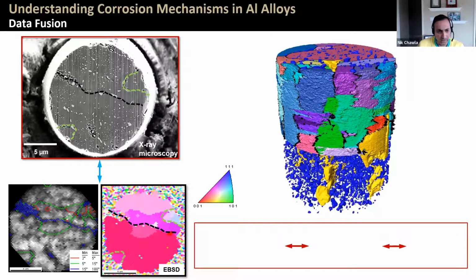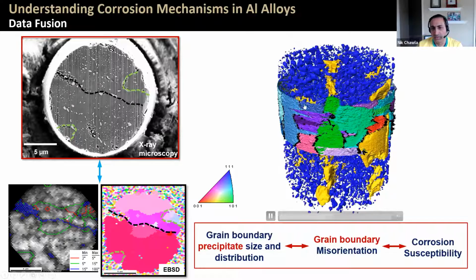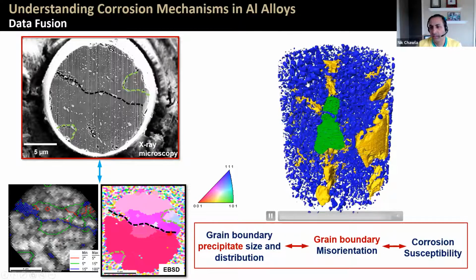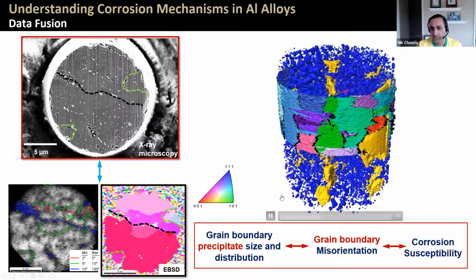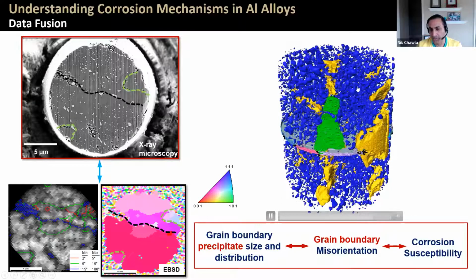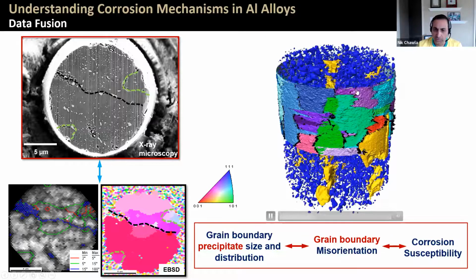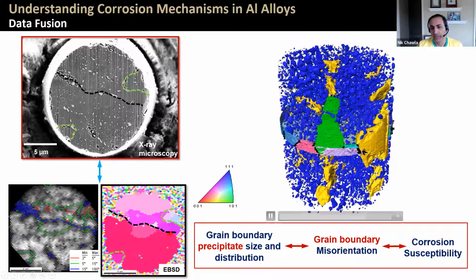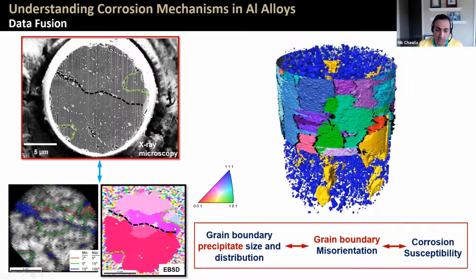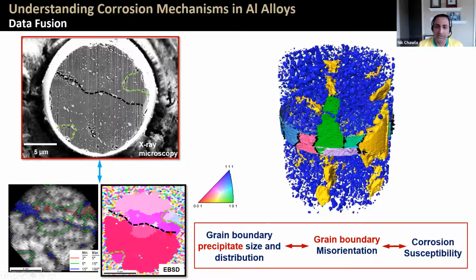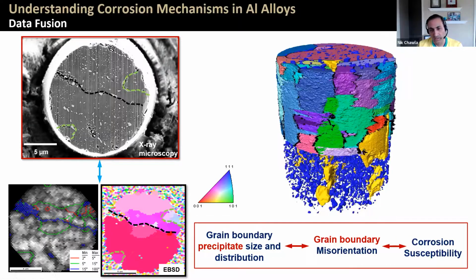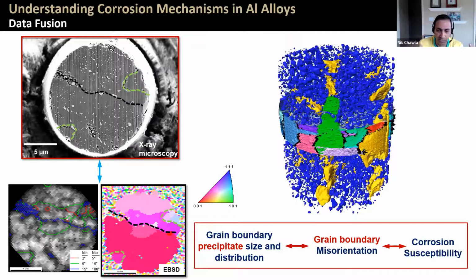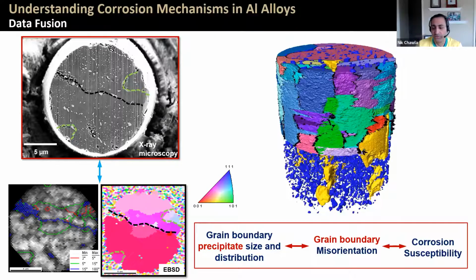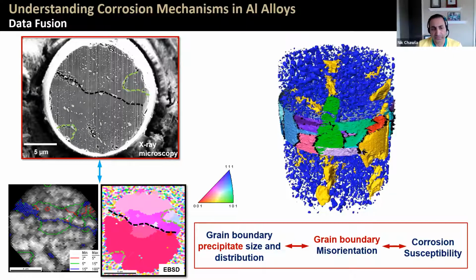And we call this data fusion because we have the imaging information, but we've also coupled this with the EBSD data. So you can see here, second phase intermetallic particles. And then you also have precipitate particles, which are actually in the blue. And then superimposed on top of that, you have grain orientations, and we could actually correlate that with the path that the intergranular cracks are taking. So precipitate density, grain boundary misorientation, and a correlation to crack growth and crack formation.